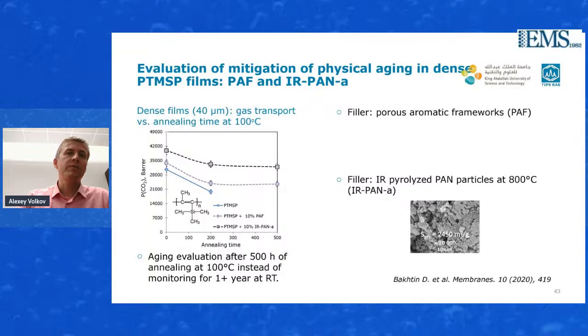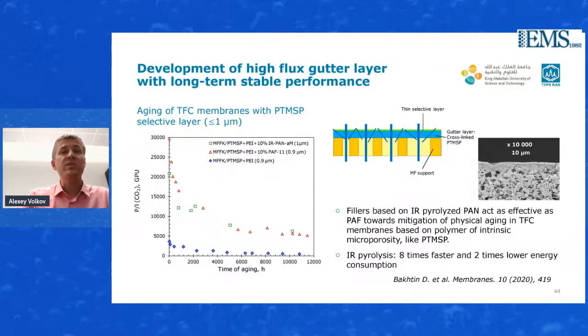We did a comparison of the porous aromatic framework that we used, a PAF that we used, with the active polyacrylonitrile active carbon. And in that case, we don't actually need to use sophisticated chemistry to make organic porous cages, but we can still use a cheap material like PAN and an affordable approach to make highly porous particles, and then get good stabilization of the PTMSP membranes in time. So we observed a thin film composite membrane for more than 1 year at room temperature, and it was possible to achieve quite a good effect from the addition of that filler to the PTMSP. Actually, that is the data.